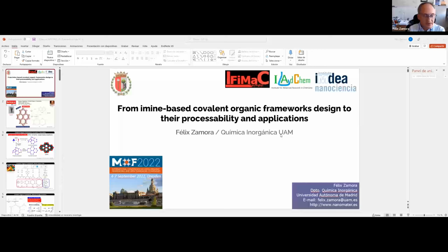No, I'm sure, because we characterize the porosity at the end of the process, and the porosity was pretty high. If you have some initial molecules in the pores, you would observe a dramatic decrease of the porosity, on the one hand. On the other, when we run the NMR characterization, solid state NMR using carbon NMR or proton NMR, you would be able to observe, even IR will give you the presence of these initial molecules. So yeah.